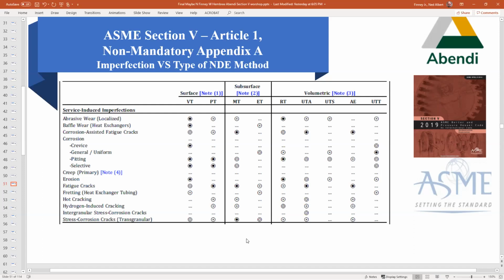So we don't have anything identified on that one. But if you go back up to the first one, abrasive wear, then you can see that VT and PT and MT and radiography and ultrasonics all the way across have some degree of finding this abrasive wear. Cracks, fatigue cracks, same thing, all of them but two are indicated.